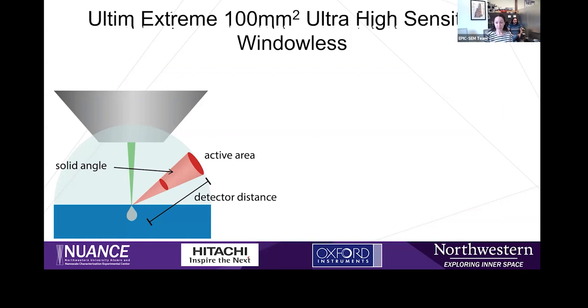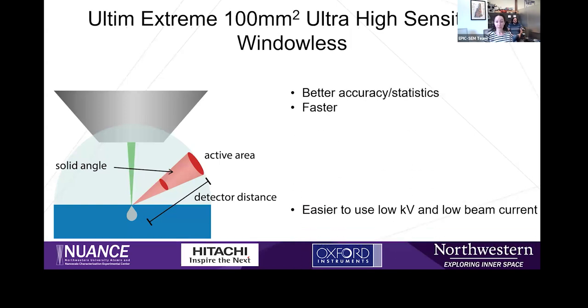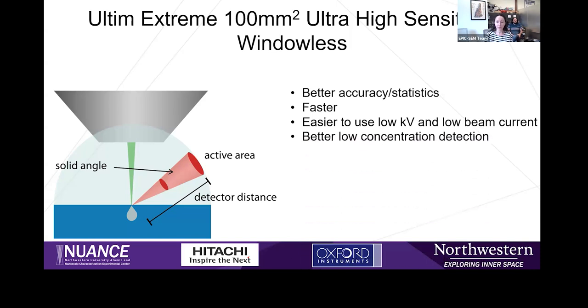And like we covered with the previous Ultimax detector, this larger solid angle means a lot of things. You'll get better accuracy, it's faster, improves signal for low kV and low beam current, et cetera, that we covered before. And because it's also windowless, it's going to be better for all those things and really great, even down to lithium. The Extreme detector is also designed with a special electron trap and a snout that allows you not to just be closer to your sample, but also allows it to be much closer to the objective lens of the microscope.